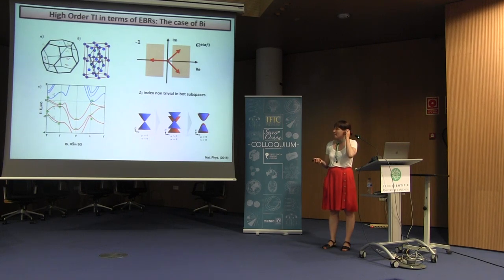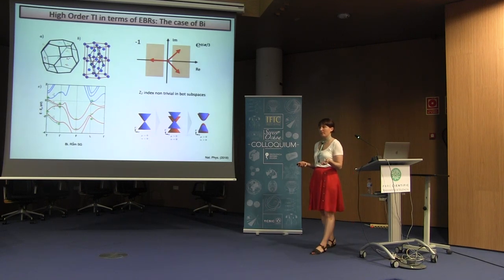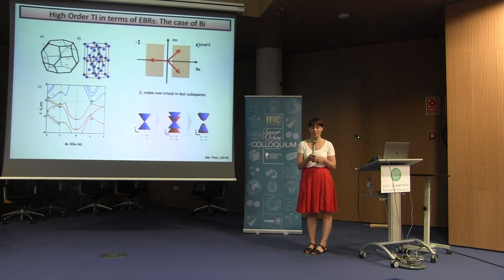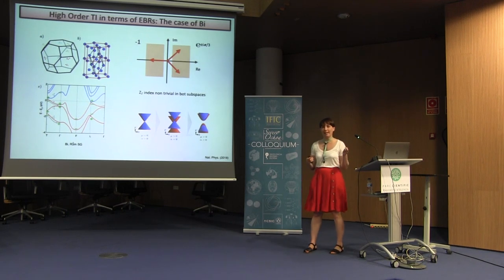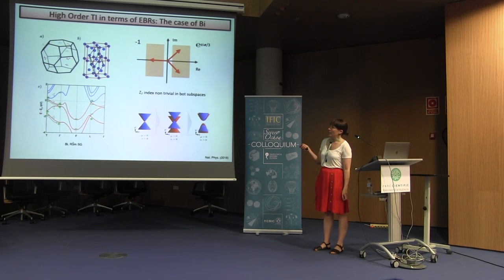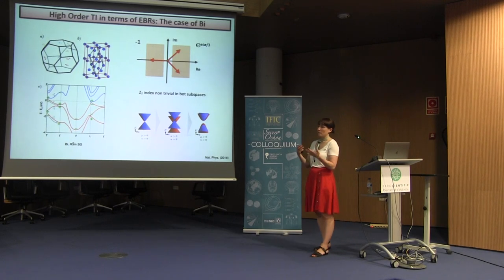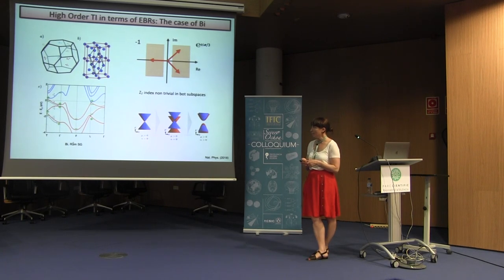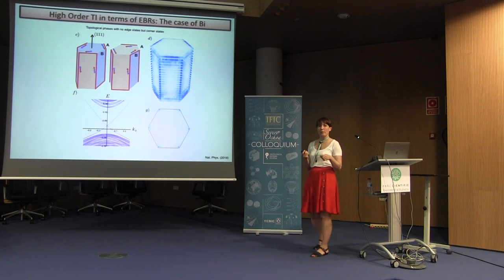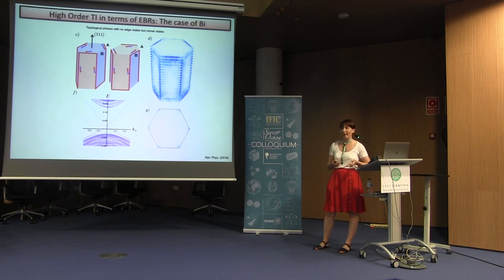There is a more mathematical and sophisticated way of understanding this. Of course, looking at the EBRs was the first step. Then the reason why bismuth is topological is because it actually has by itself two topological phases. So the C3 rotation eigenvalue has two subspaces, one for eigenvalue minus one and the other one for these other two eigenvalues, and in each of the subspaces we have a topological phase, and when we go to the surface they get gapped. But there must be a charge flow. You cannot have a topological phase that is strong and doesn't have a charge flow.